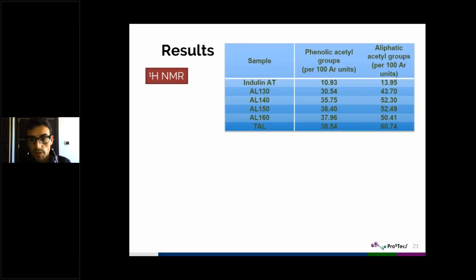By hydrogen NMR, we can quantify how many of these hydroxyl groups have been transformed into acetyl groups. So we can see for the phenolic acetyl groups, again, as we increase the temperature, we obtain higher quantity of these acetyl groups formed, in the inverse case of what happened with the hydroxyl groups. However, for the aliphatic acetyl groups, what was happening is that from 130 to 140, we're having a high increase of these acetyl groups, but from 140 to 160, those values are more or less constant.